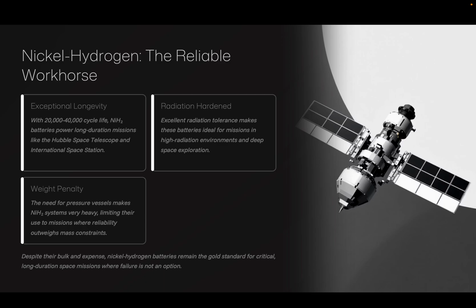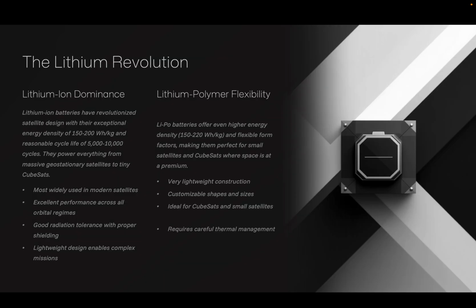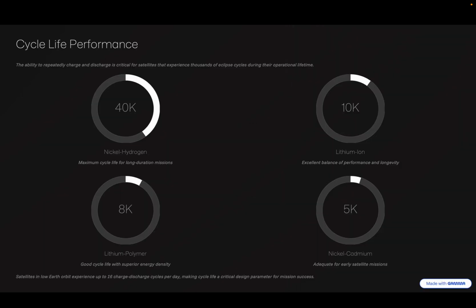So we can choose nickel hydrogen batteries over the nickel cadmium batteries. And if you see the lithium ion or lithium polymer batteries, these have better life cycles. The cycle life of lithium ion batteries is 5,000 to 10,000 cycles, and the energy density of lithium ion batteries is 150 to 200 watt hour per kg. Similarly, lithium polymer batteries have almost the same density, and the lifespan is also almost the same as lithium ion batteries.